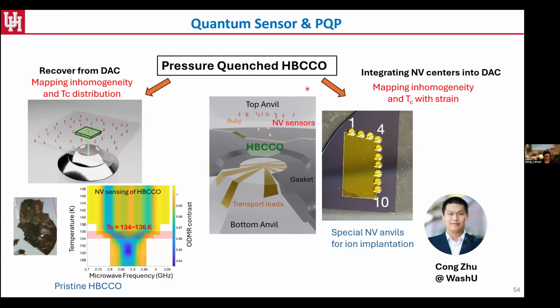And lastly, recently, we're also in collaboration with Cong Zhu's group at Washington University in St. Louis. They have those nice quantum sensors used in the NV technique. The importance is it gives us a very nice tool that can really map the inhomogeneity and the TC distribution before and after the pressure quenching. Because intrinsically, when you're under pressure, the pressure medium we use is not super homogeneous. So we would imagine even under pressure, the TC distribution on the sample is not going to be ideally homogeneous, not to mention after this very ruptured pressure quench.